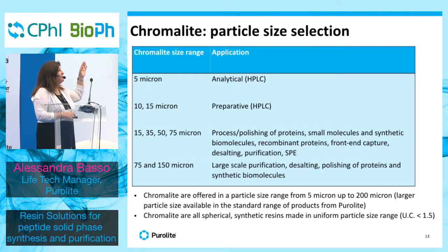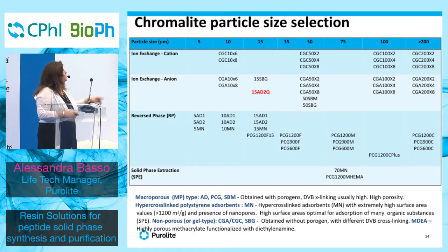So we start from 5 micron, analytical HPLC. We are working to go down to 3 and 4. We are still working on that. So we have 10 and 15, which is really the preparative HPLC that works for peptide purification. And then we go up to 75 and larger particle sizes, which is more for different kinds of molecules, typically for purification of molecules made by fermentation. So for peptides it is really 10 and 15 micron. In the product line, you see all these kinds of products.